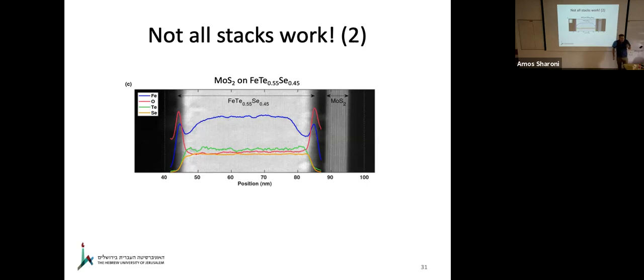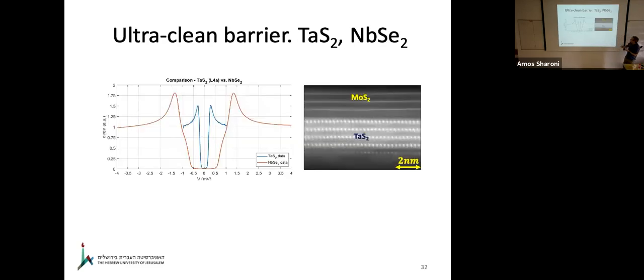We need certain sets of materials which engage well together, and it looks like materials from the transition metal dichalcogenide family, like molybdenum disulfide and tantalum disulfide, engage very well. This is work of my student Shachar Simon. This is the superconductor tantalum disulfide. It's 4 layers thick. This is the tunnel barrier, molybdenum disulfide. And as you see, they're perfectly engaged. So that's as good as you can ever expect. That's atomic engagement with this very, very simple fabrication methodology of pressing these two materials one on top of the